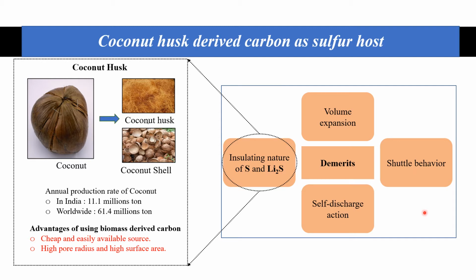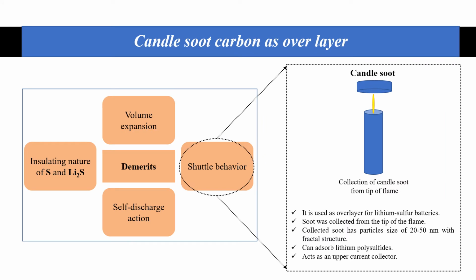Lithium-sulfur batteries suffer from several challenges such as the insulating nature of sulfur and Li2S, volume expansion during the electrochemical reaction, shuttle behavior, and self-discharge. So to avoid the insulating nature of sulfur, here coconut husk derived carbon was used as sulfur host, whereas to avoid the issue of shuttle behavior, candle soot carbon has been investigated.